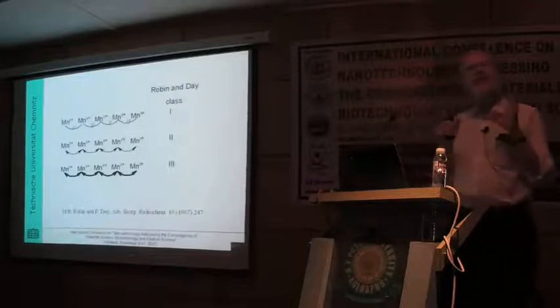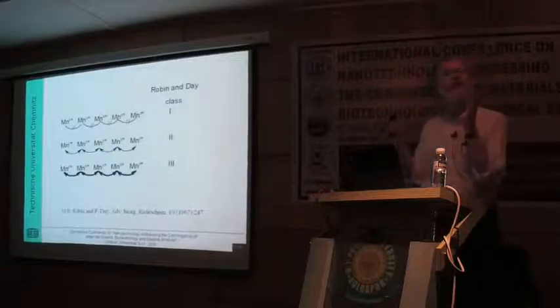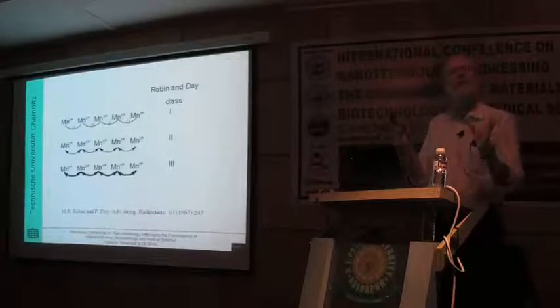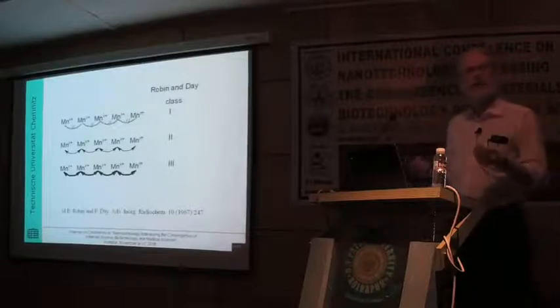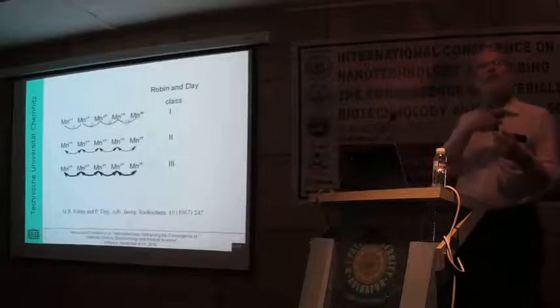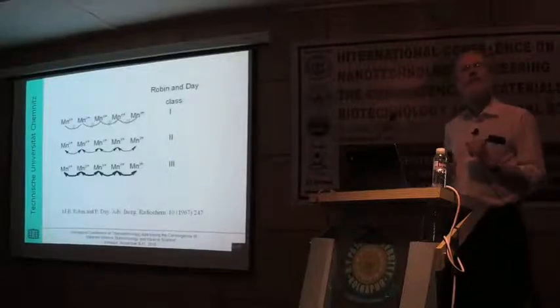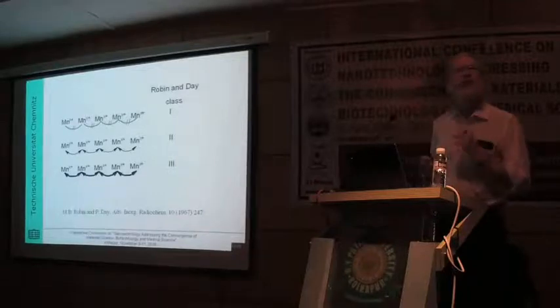If there is no interaction between the manganese ions, in theory, we will not observe it, but in theory, all manganese ions will be oxidized at the same electrode potential. In that case of no interaction, we will observe indeed a very beautiful current peak. This idea was not at all new.